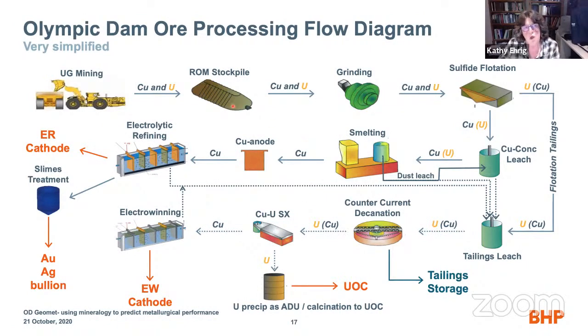So here is a grossly simplified flow chart for Olympic Dam. Underground mining, dirt gets put onto the stockpile. It gets ground down to 75 microns, and then we go through a sulfide flotation, no different than a whole lot of other people. This making a concentrate is where most places stop. Most sulfide concentrates, you make a concentrate and you ship it someplace else to be smelted and refined. At Olympic Dam, that's kind of almost the beginning.